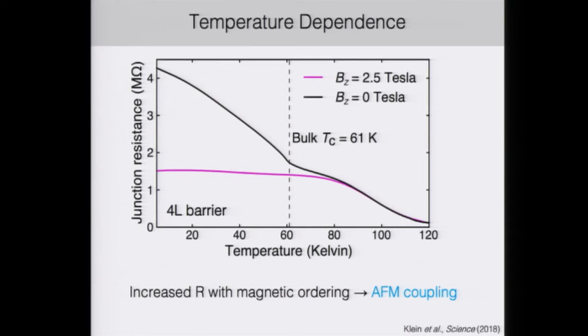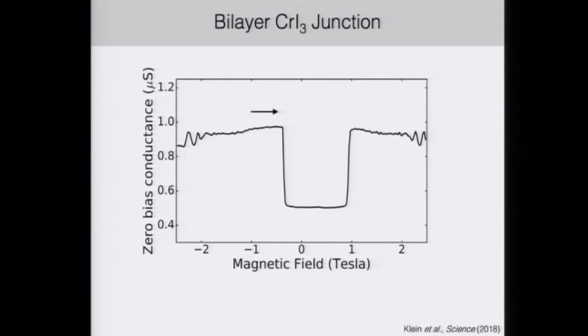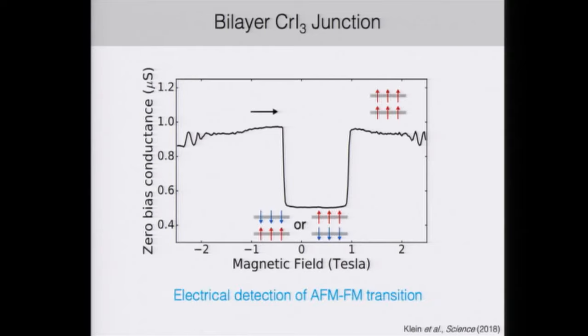ordering is suggestive of antiferromagnetic coupling, because you can think of the spin filter effect as filtering out spins in opposite directions between adjacent layers, which will result in a higher overall resistance compared to the paramagnetic state above 61 Kelvin. Now, if we looked at the zero bias conductance as a function of magnetic field for bilayer chromium iodide, we see this very discrete step between low and large applied magnetic fields. And so what these two states are is the direct electrical detection of the AFM-FM transition in chromium iodide.